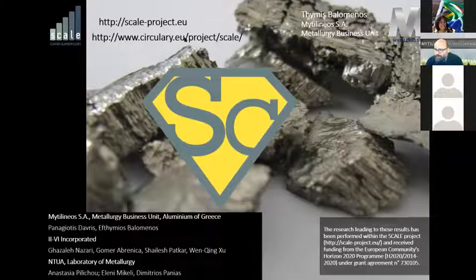There is no way around it, you will have to start adding lime to neutralize everything until it's made into water that can be safely disposed. Adding lime, of course, means adding CO2 to your process and so on. So therefore, it could be a burden in terms of the raffinate unless the raffinate can be recycled into the process. Other than that, it will not add any real problem in terms of energy consumption. It doesn't add a lot. In terms of acid consumption, as I said, it's 0.3 per ton of bauxite residue, so it's not a huge amount.